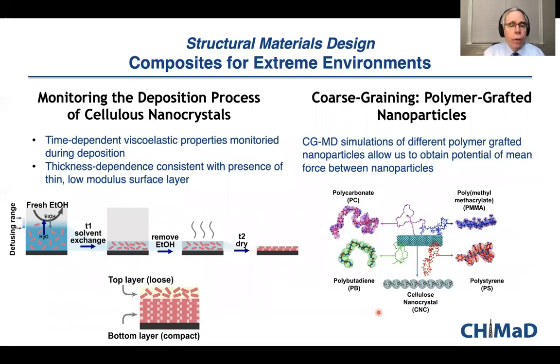And so what the group is focused on most recently, for example, is how you deposit cellulose nanocrystals, and how these cellulose nanocrystals can be deposited in a way where you understand what the modulus of the surface layer and the viscoelastic properties of this layer are. And in order to guide these experiments, there are coarse-grained molecular dynamics simulations of polymers that are grafted to these cellulose nanoparticles. And using this insight, you can understand how to process these materials to give you the properties that you need.